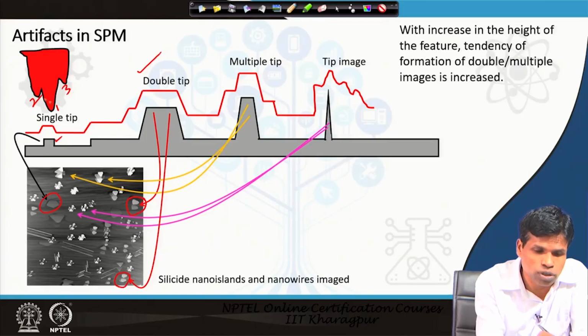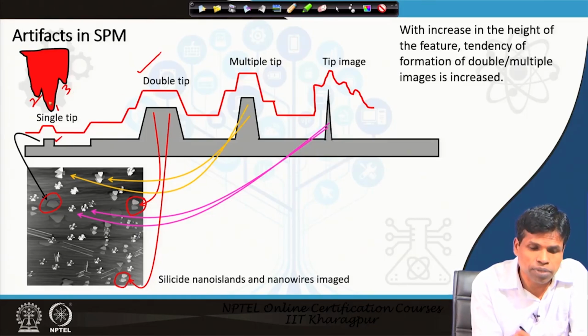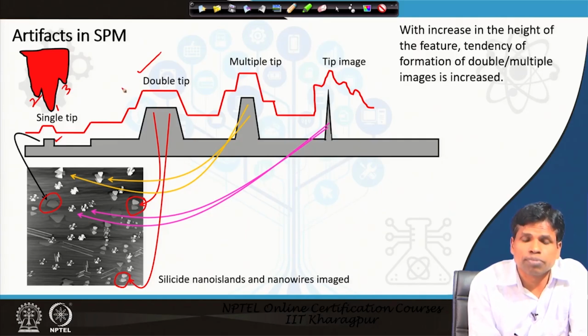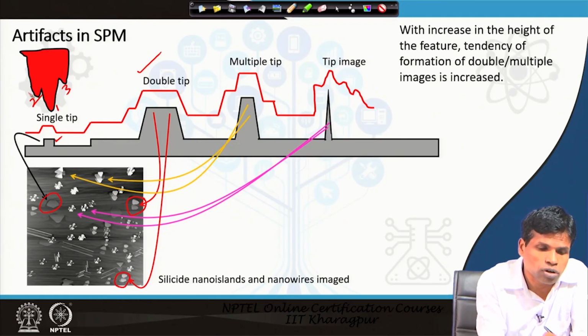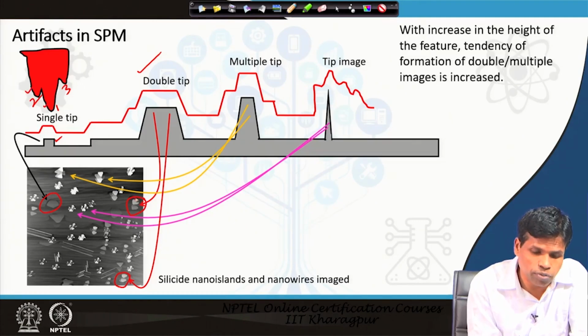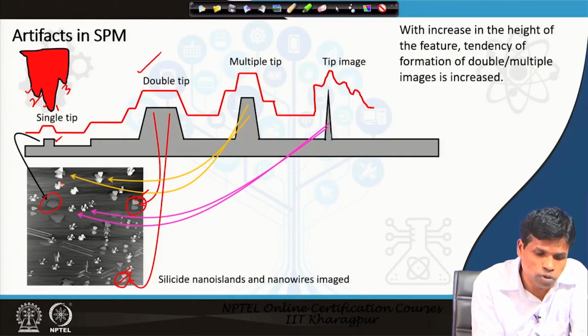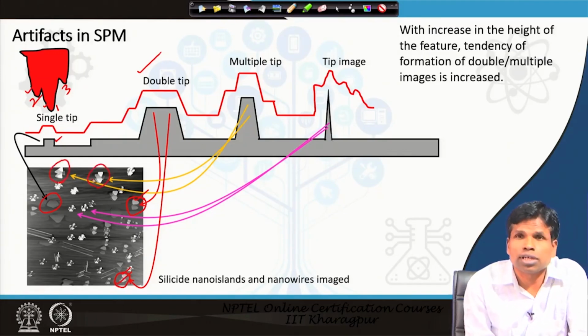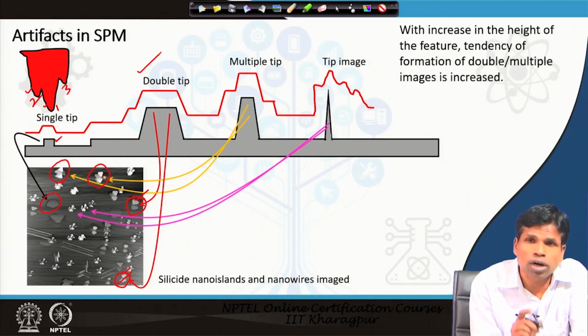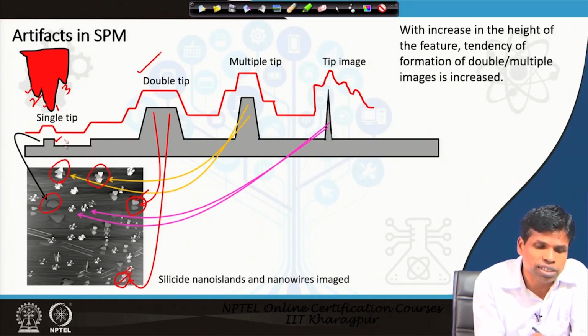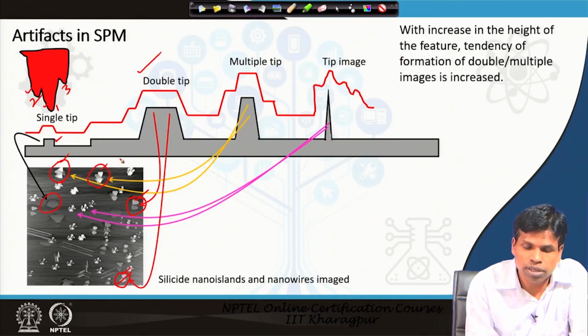This is due to the double tip. 2 tips are measuring the current at the same time, and the voltage is also measured at the same time, because they are being measured in constant current mode. So, these 2 voltages are going to 2 different tips, giving 2 different data points. That is why the same structure repeats. Here you see multiple such structures. In each of these structures, there is actually one feature, but each tip is measuring it. As each tip is measuring it, that is why the repeated information is being seen here, the multiple tip effect.